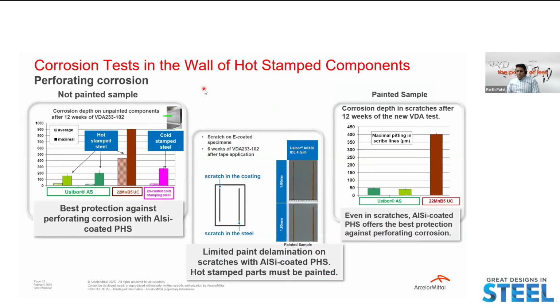So why AlSi coating? It's one of the best performing coatings for perforation corrosion. This is a test, VDA 233-102, a scratch test. You put a scratch in the steel and the coating, and measure the depth of corrosion after 12 weeks - there's a spec that says 6 weeks, but we've done it in harsher environments. It's a cyclic corrosion test with multiple acids, and when you measure the depth, for AlSi-coated steel it's actually less than zinc coated steel. So for perforation corrosion, it acts better than zinc coated. Of course it's better than uncoated material, but it's much better than zinc coated as well. There's a perception that GI is better than AlSi coating, but actually for perforation corrosion, it's much better than GI coating.